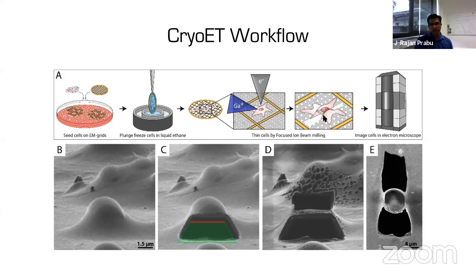You really cannot image a complete cell because it's too thick. You need something with a 200 to 300 nanometer thickness. What you do is focused ion milling, which I have a movie to show, and then look at them in the microscope. This is how it looks. And then you mill them away. This is called a lamella, which is really, really thin.